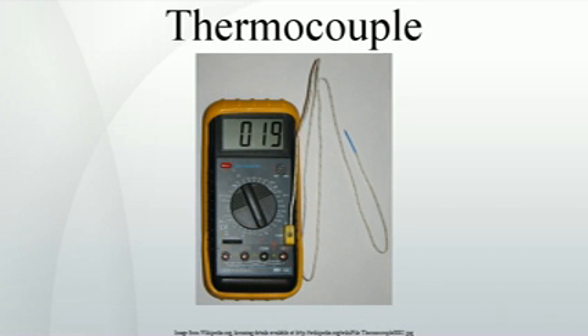Another source of drift in Type K thermocouples is that near 400 °C, a slow reordering in the chromel wire occurs. This is reversible and leads to hysteresis between heating and cooling. Type M. Type M, Ni-Mo 82%/18%, Ni-Co 99.2%/0.8%, by weight, are used in vacuum furnaces for the same reasons as with Type C, described below. Upper temperature is limited to 1400 °C. It is less commonly used than other types.